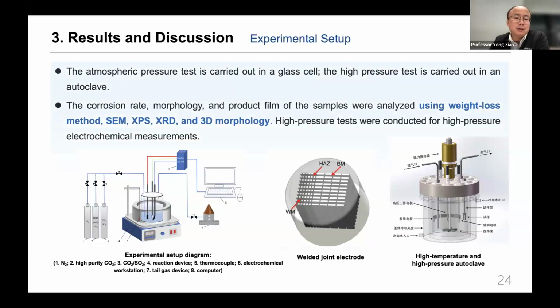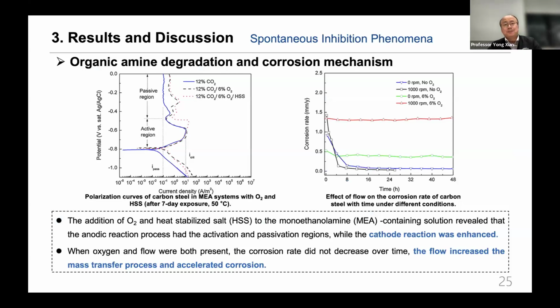In our work we used a glass cell, and we also used a high temperature and high pressure autoclave to create the corrosion environment. We also studied the welded joint electrode. Here we have the weld metal in this area, the heat affected zone is this area, and the base metal is this area. So we have some results to show you. This work I did 10 years ago at Ohio University.